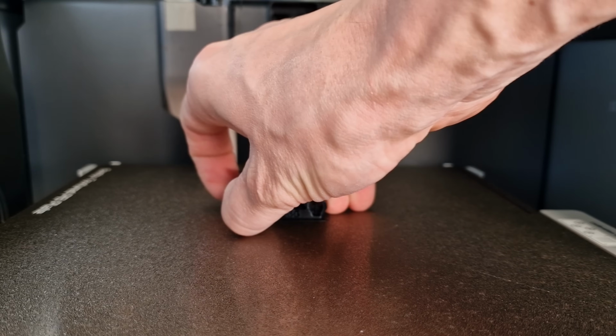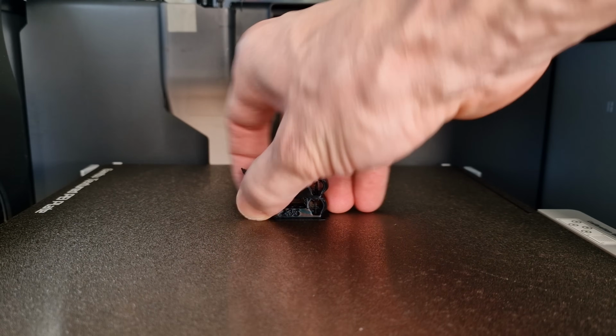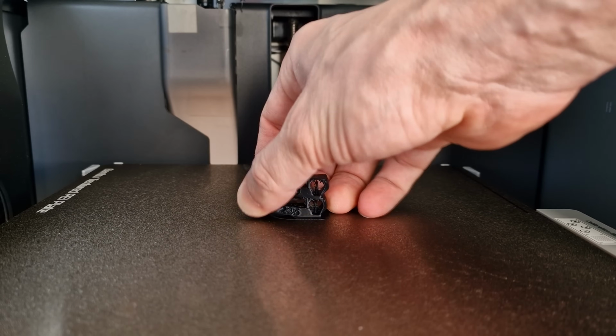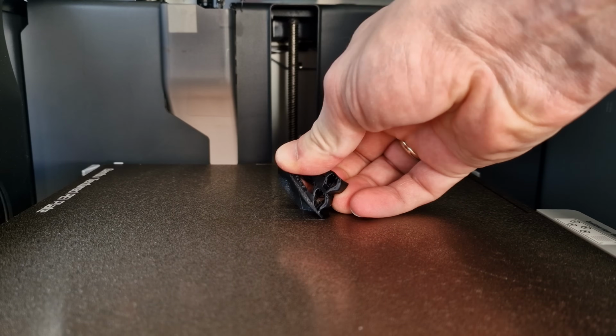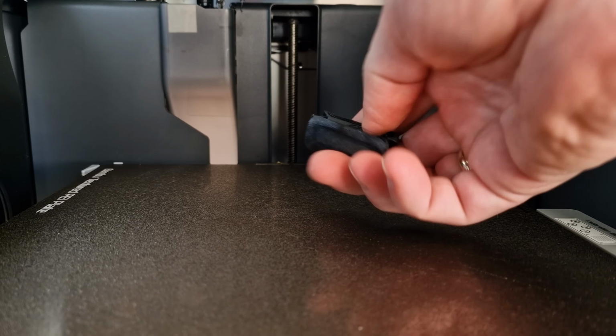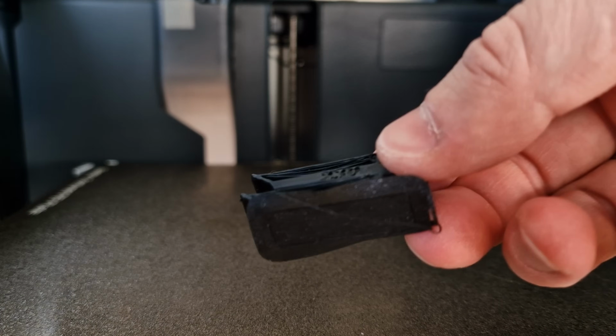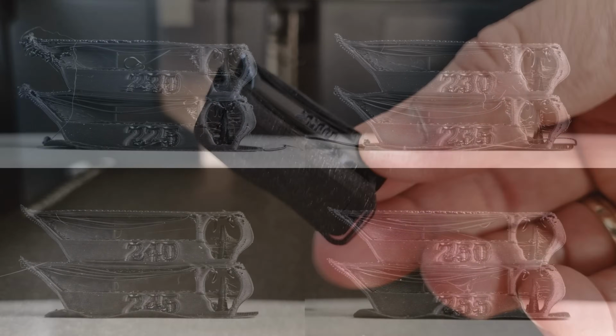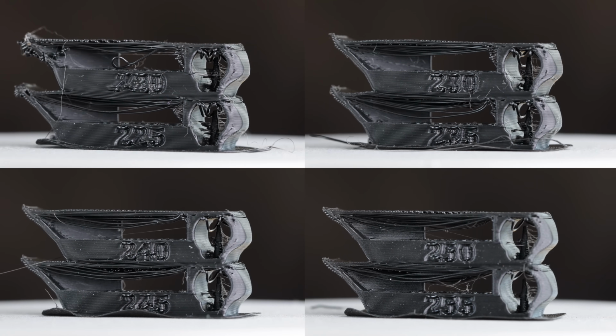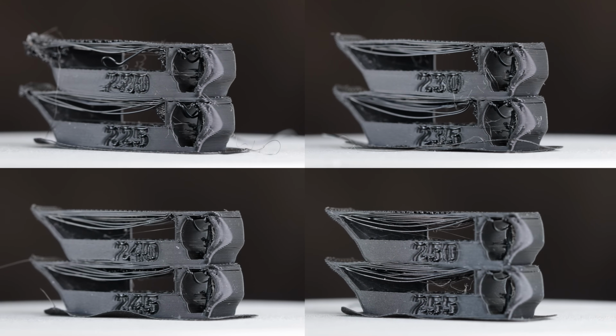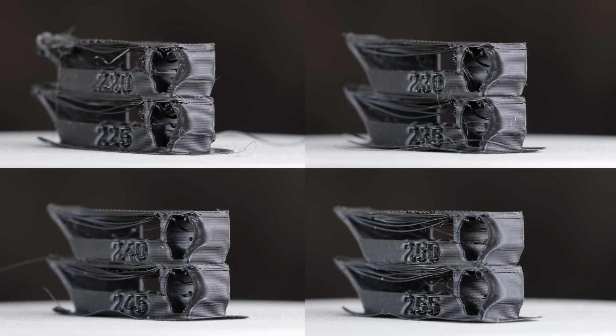As you can see, the material adheres really well to the print bed. For reference, I didn't use any glue or separation layers. If possible, I prefer to avoid those since they just create more cleanup work. Here are our 4 completed temp towers, covering the temperature range from 220 to 255 degrees Celsius.